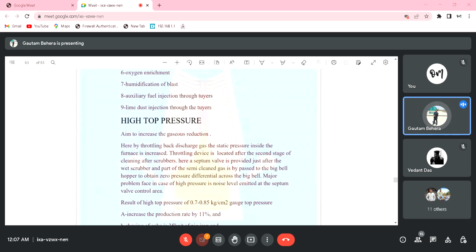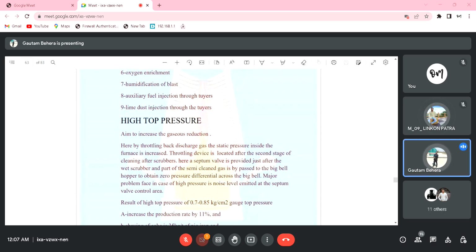So in the shaft region or in the stack region, which kind of reduction is going on? Direct or indirect? Mostly indirect reduction. Indirect reduction means carbon monoxide will react with iron ore rather than the direct carbon, right? So if you inject carbon monoxide through the stack by installing some pipes, it will obviously increase the rate of reduction, right?